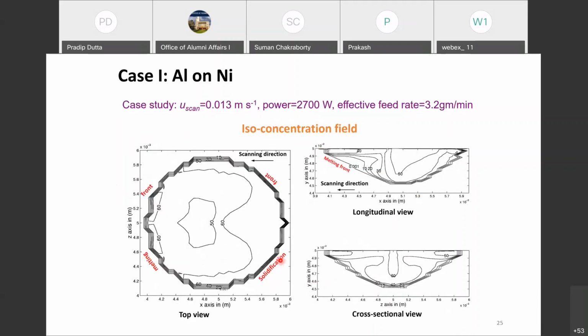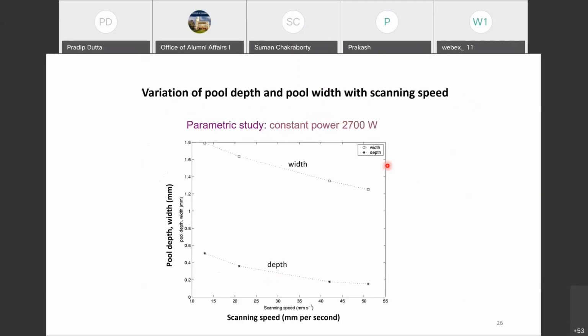And then of course the concentration field also we can predict over here. Based on the concentration, we would know at the interface what kind of microsegregation is happening, and what kind of concentration the alloyed material has, right? And we do certain other parametric studies, which basically show that as the speed of the laser increases, the depth decreases and the width can also decrease, because the weld pool volume actually decreases with speed, which is predictable, but we just wanted to quantify it with our model, but that is intuitive also.